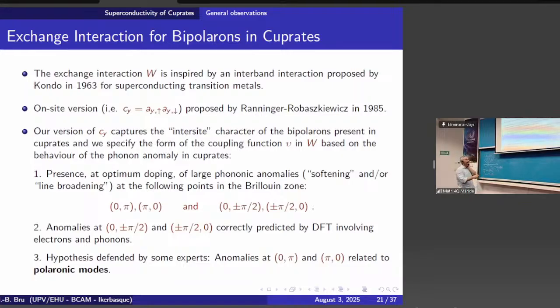For this one, the anomaly is due to a softening of the phononic energy. It means that the phononic energy, the spectral energy, I mean the energy of the phonon with respect to k, decreases a lot when you reach (0, pi). It's more or less constant, but then it decreases a lot. So for (0, pi), something happens. And for the other one, if you look at the response, you see that for this mode k, the response is not sharp. It has a broad response in terms of phononic excitation.